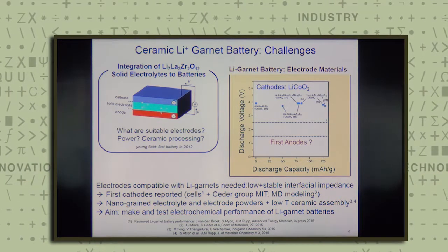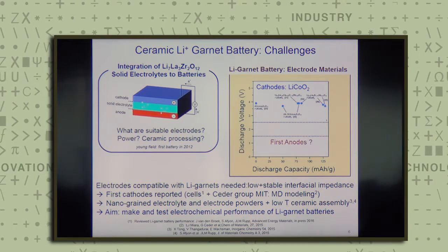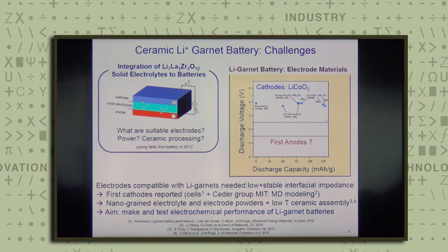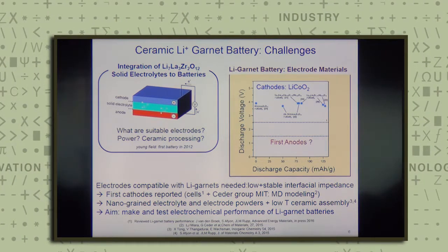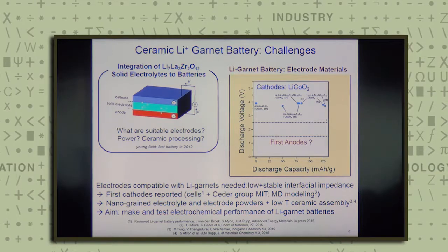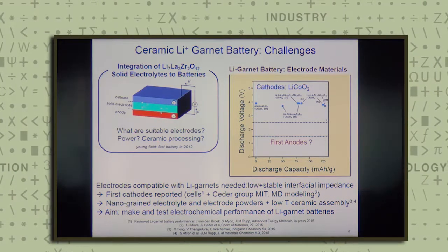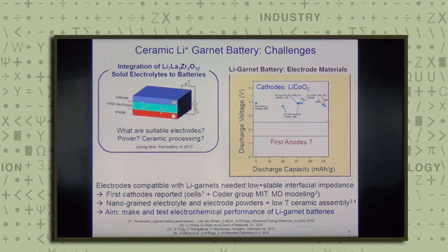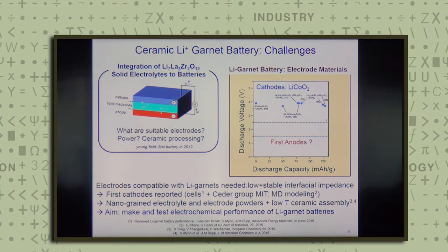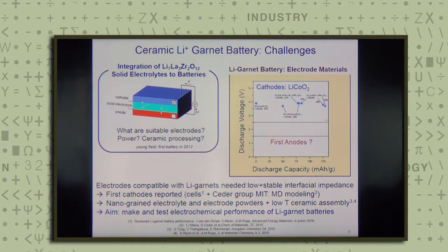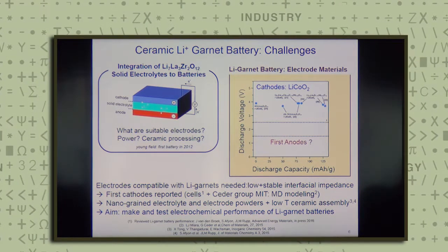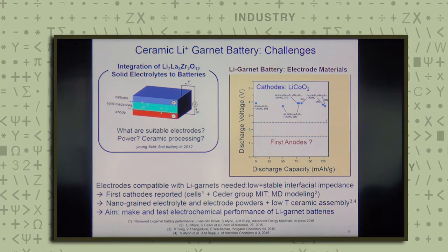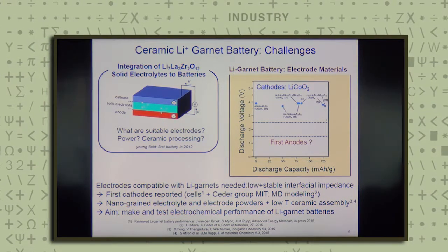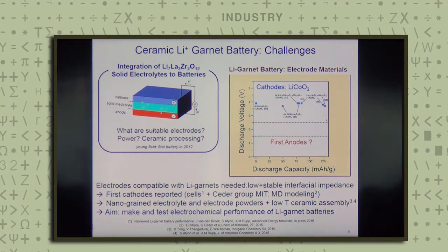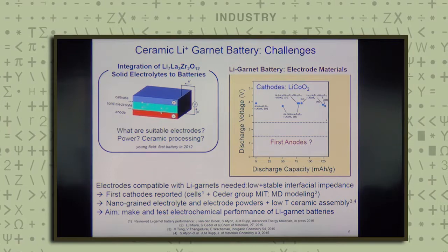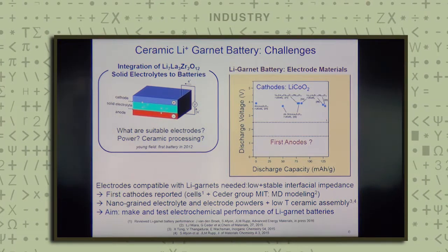One challenge is very simple. If I plot here on the right side a careful literature analysis, then apart from lithium, where obviously we have some safety concerns if we directly use this, there's not one single anode that was published until last year on an oxide that has been composed into a full ceramic battery cell. Also, if we look at the cathodes, some of the materials are still very limited. That means the ceramic processing still has a very long way to go to integrate alternative anodes to make open geometries and profit from the ability of these lithium ceramic structures. And to find good low-temperature ceramic processing techniques is of essence, and also to suggest new materials.